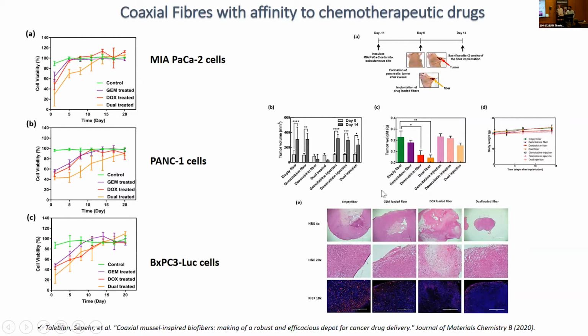And then when we did the histology on the tumor tissues that were treated with different formulations, we observed, especially with Ki67 marker, which is a marker of growing and dividing cells, that the dual treated fiber had the least amount of dividing cells, which is promising. What we're trying to do is slow down the growth of these tumors.